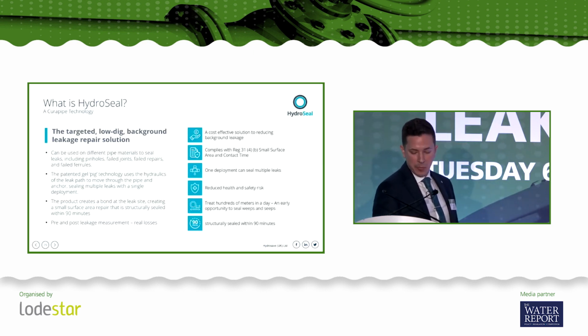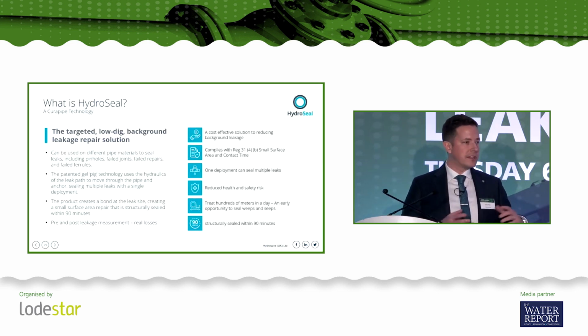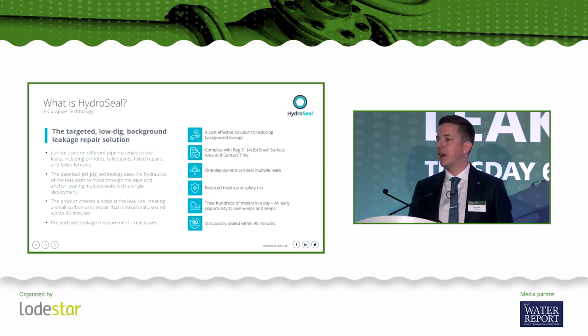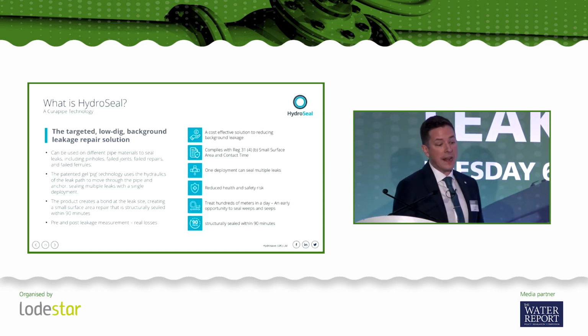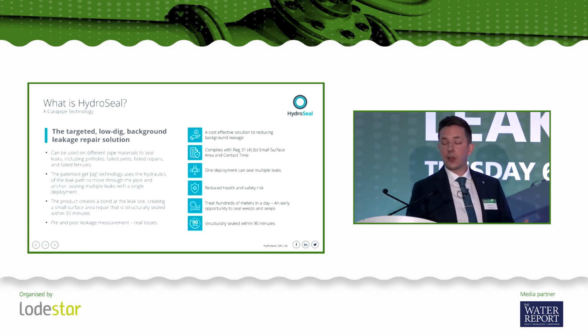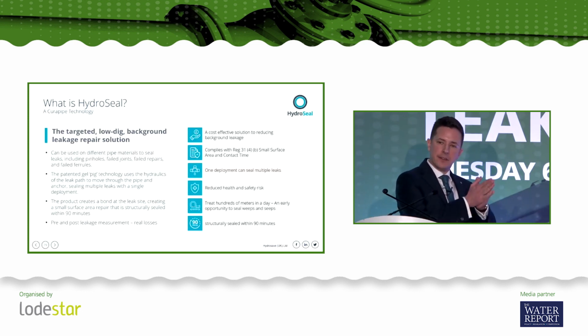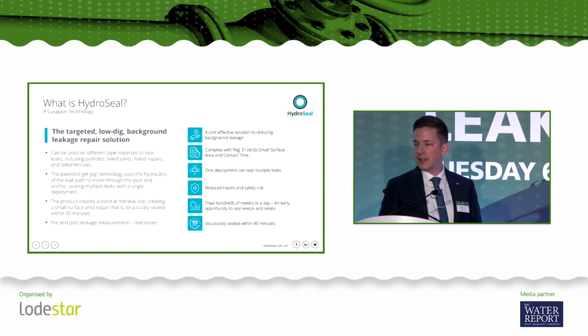How does it work? It anchors and it bonds to create that bond at the leak site. The testing so far out of Israel suggests a 10-year asset life, albeit some of our testing suggests that it could be as much as double that as well. So the benefits of this type of method, we believe it's a cost-effective solution to reducing background leakage. It complies with Reg 31(4)B, small surface area. In one deployment, you can seal multiple leaks. We believe there's a reduced health and safety risk when compared with traditional excavation methods. And you can treat hundreds of meters in a single day, giving us, as an industry, an early opportunity to seal weeps and seeps before they become worse. And after the deployment through the pipe, it is structurally sealed within 90 minutes.